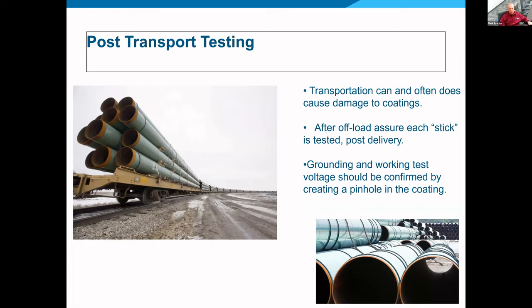That's correct, Tom. So post transport, especially on pipeline, you've got vacuum grabbers picking these things up and dropping them onto trucks and trains, and coating often gets damaged. So we want to make sure that after we get it off of the train, that coating is in good shape, or that we find the holidays. So after the unload, you make sure that every stick of pipe is tested, every tank is tested over the entire surface.